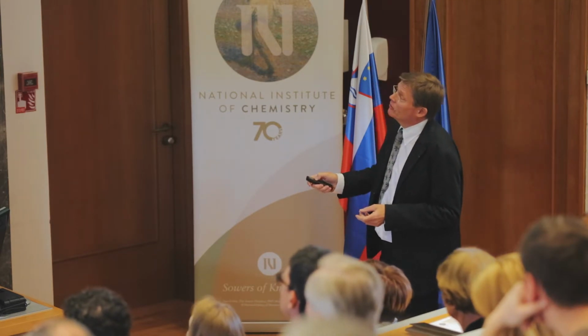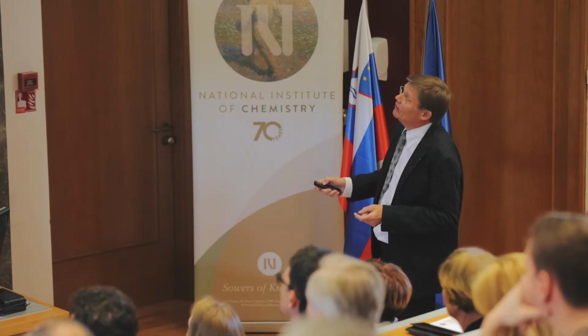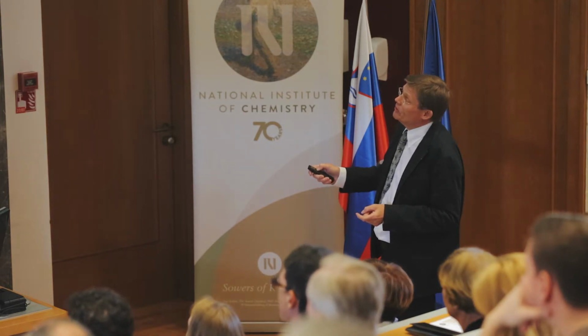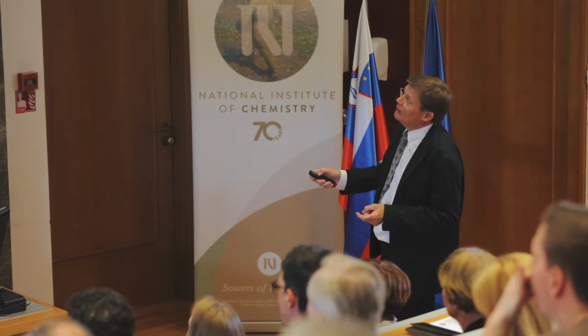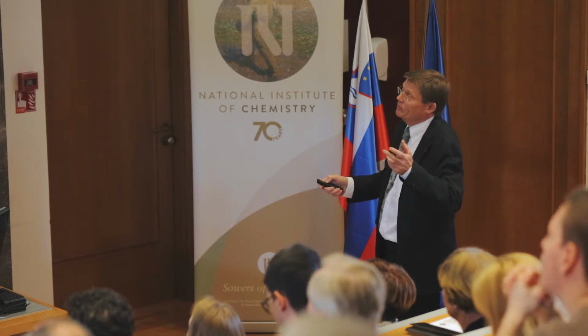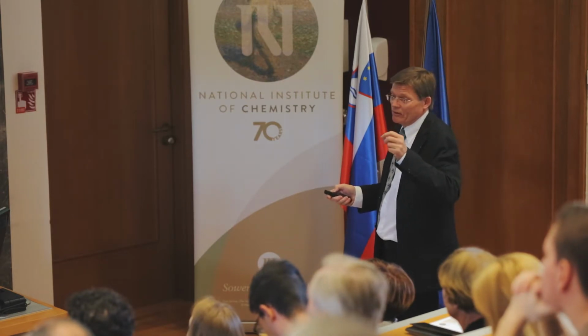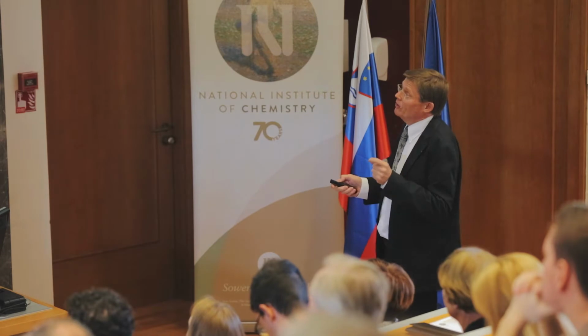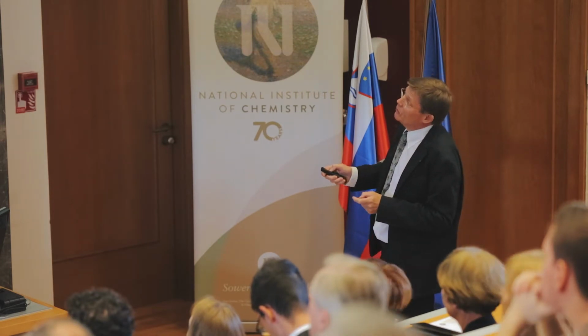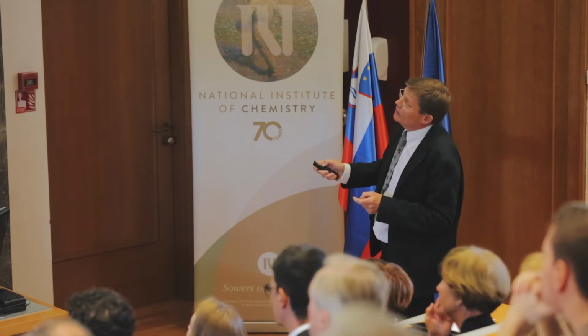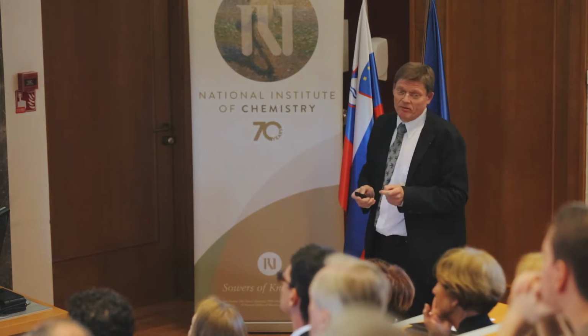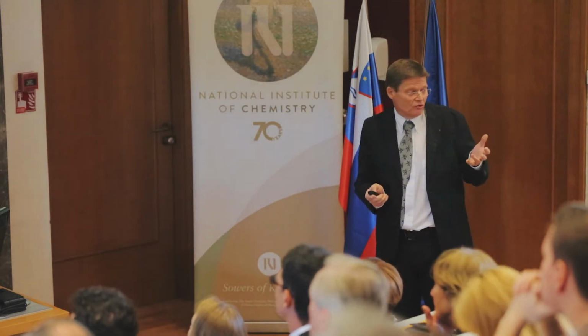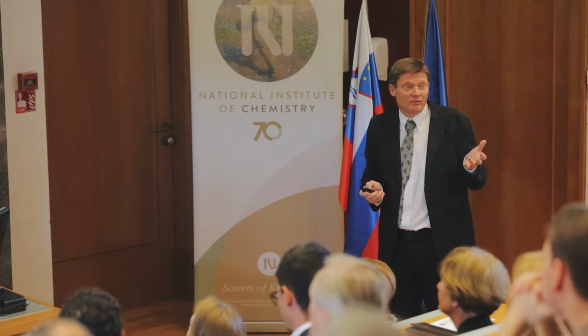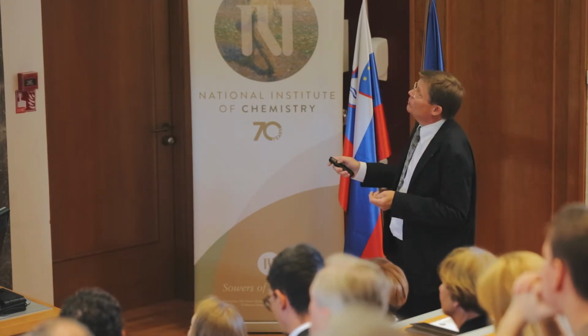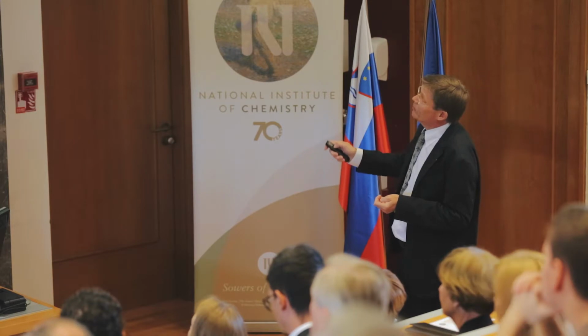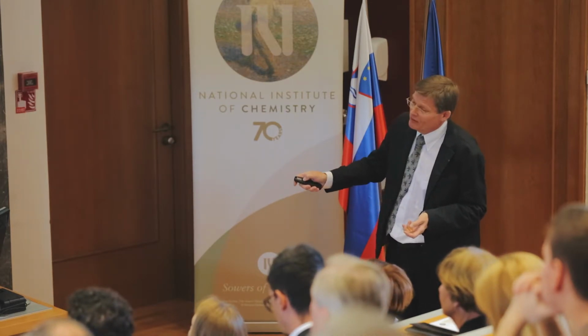So we took this equivalent circuit, a simplified version here. This is capacitance as a function of frequency. Sorry for this misprint here. That is, for specialists, the real part of the complex capacitance. Anyway, it goes up. This is a bulk value here, and this is a chemical capacitance. So it's a chemical capacitance which makes this very high value. When you do this kind of sweep experiment, this is hysteresis. It's just coming through this equivalent circuit.